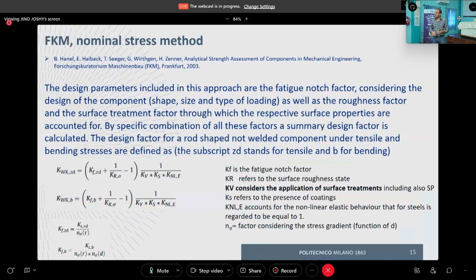KWK means the design factor for fatigue. ZD means for tensile load. B means for bending. And here we see these formulas, where we can recognize KF is the fatigue notch factor. KR is referring to the roughness. KV considers the application of possible surface treatment, and this includes also shot peening. So shot peening is included in this KV factor. KS refers to possible coating, if any, of course.